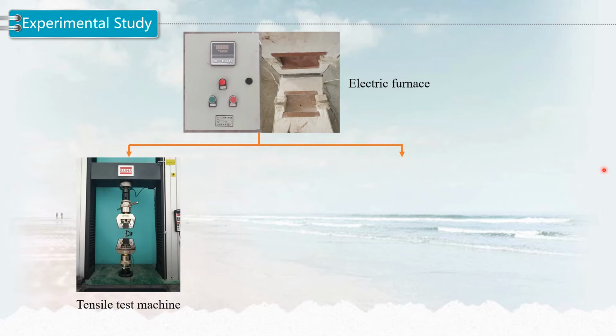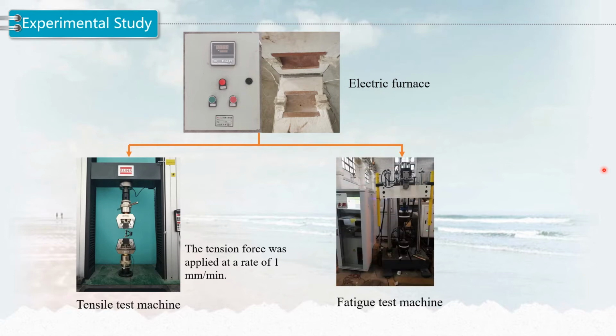To study the mechanical properties of steel wire after fire, an experimental program was designed. It mainly consists of 2 steps. First, heat the specimen to the desired temperature by an electrical furnace and subsequently remove them from the furnace and cool down to room temperature. Second, conduct tensile test and fatigue test on specimens. All specimens in this test were identical to the ones used in the Suspension Bridge.